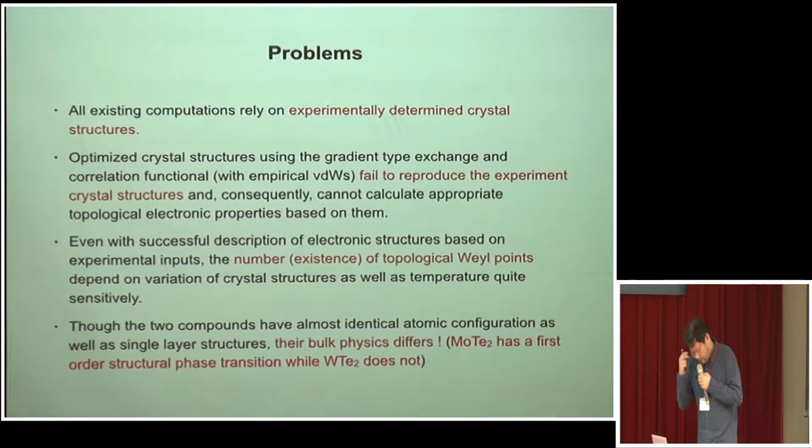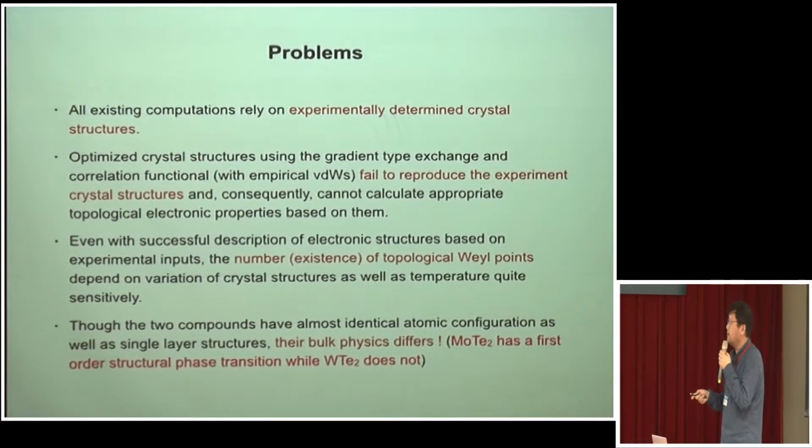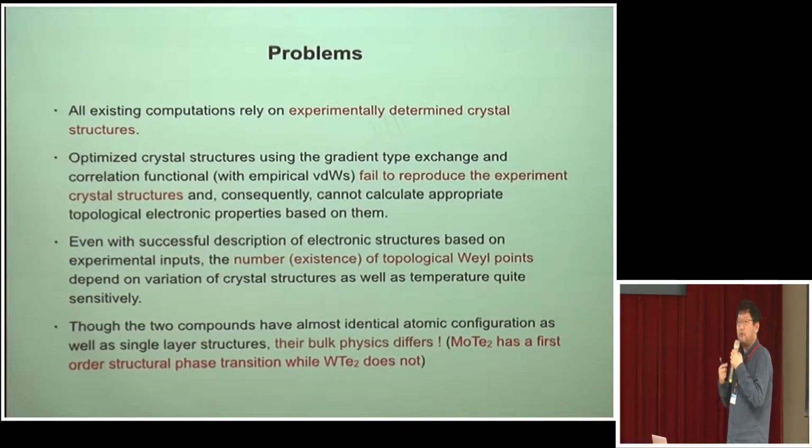The problem for this material is that, as far as I know, all existing computations of the electronic properties rely on experimental input, because first principles cannot reproduce the crystal structure determined by X-ray. So if you obtain the atomic structures using first-principles calculation, you actually cannot reproduce the topological properties.